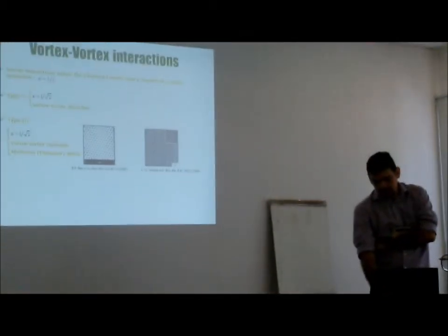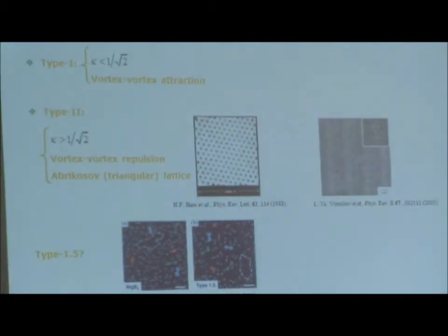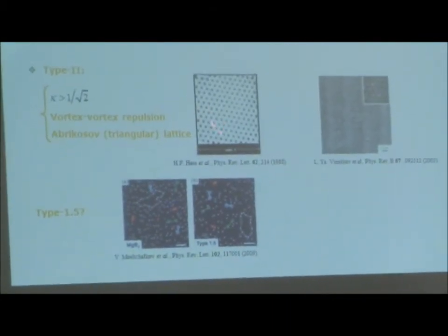And so, okay, until here we knew everything that happened. I mean, we were quite used to the theory. But then there was a very controversial result that appeared a few years ago, by this group from Leuven, right? This doesn't match either these cases here, nor a type 1 superconductor. It actually shows some positions of vortices that form pairs or some domain like that. So this was very weird if you take into account only this theory.